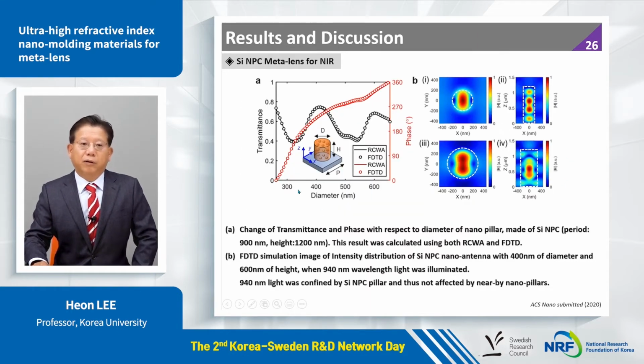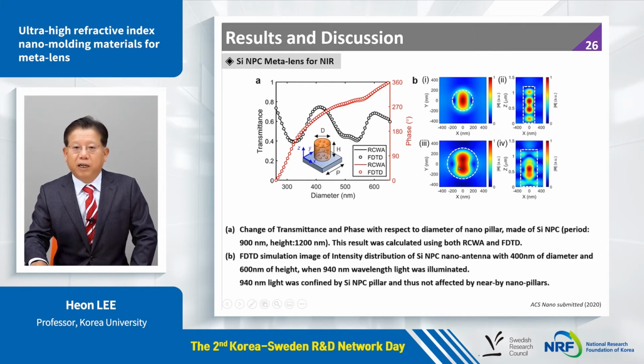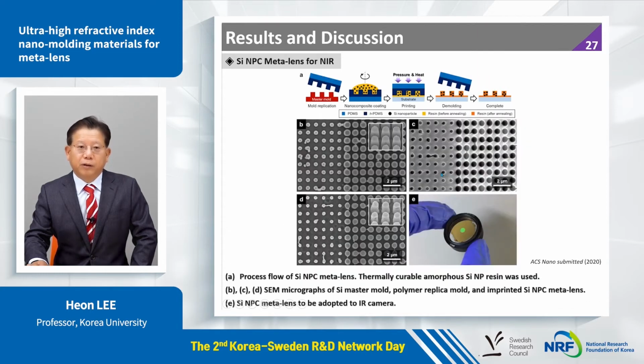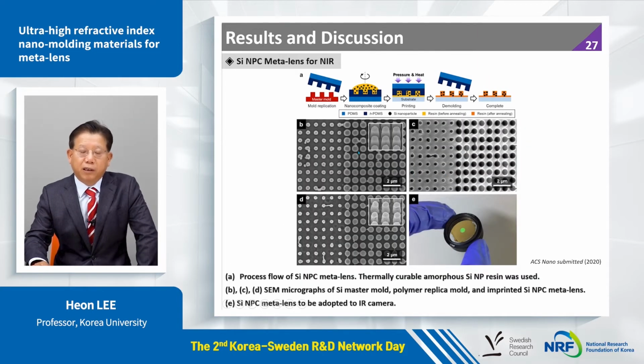By adjusting the diameter of the nanocylinder from 250 to 650, I have 0 to 2 pi of the phase change. And incoming light is well defined by a single nano antenna based on the simulation. So here is the experimental result example. This one is the SEM image of the master mold. B is a master mold, C is the polymer replica, and D is the imprinted meta-lens.